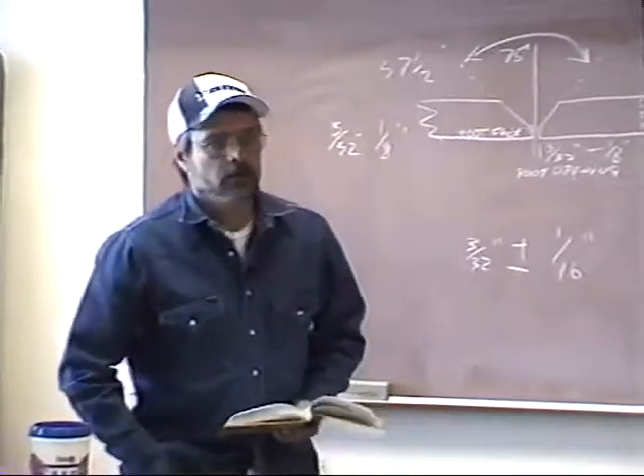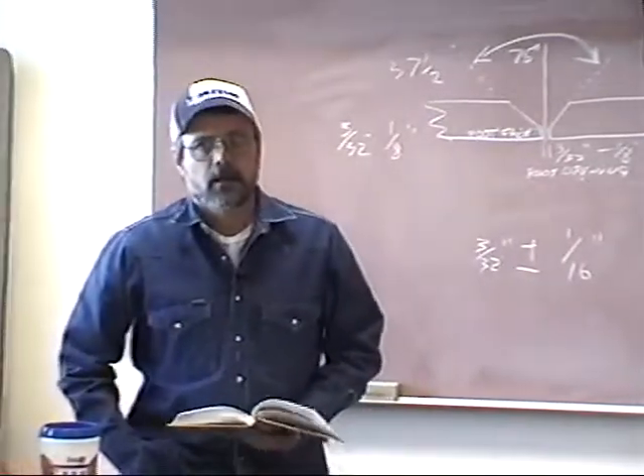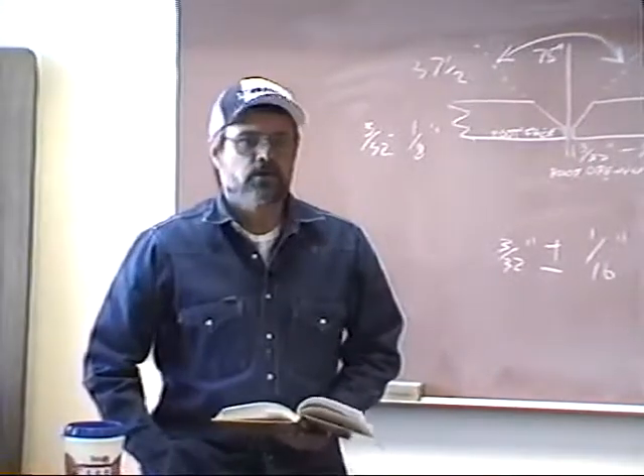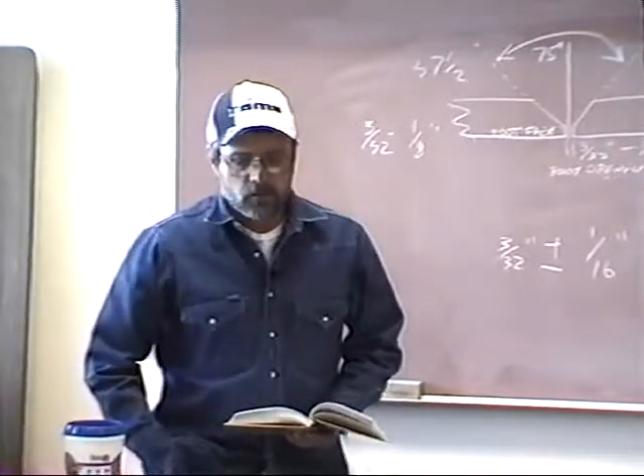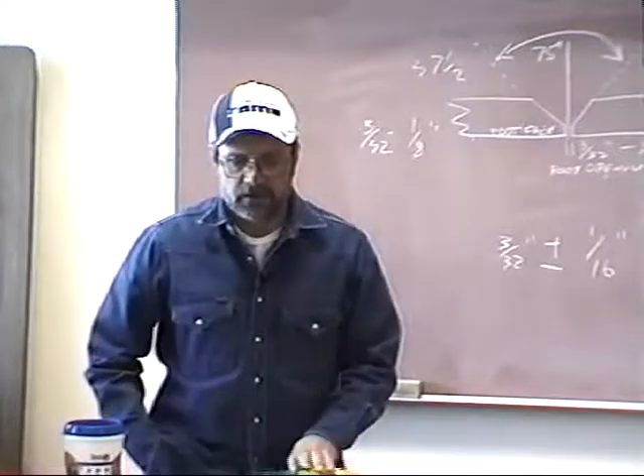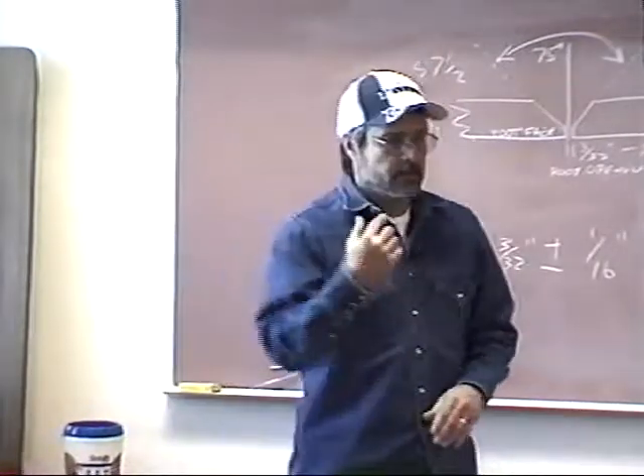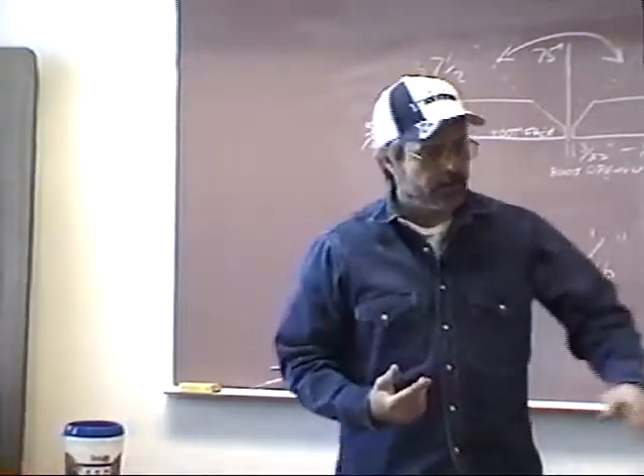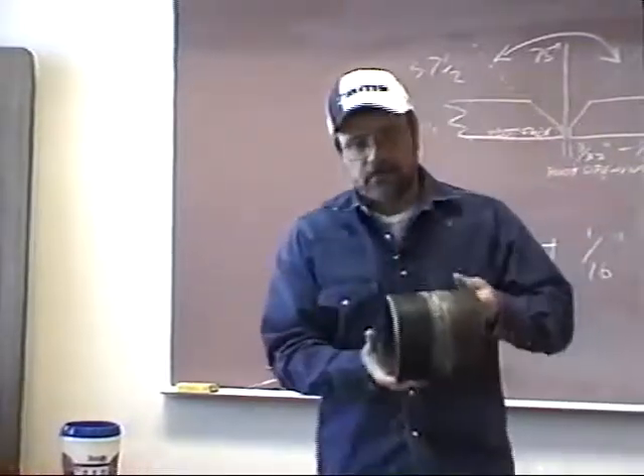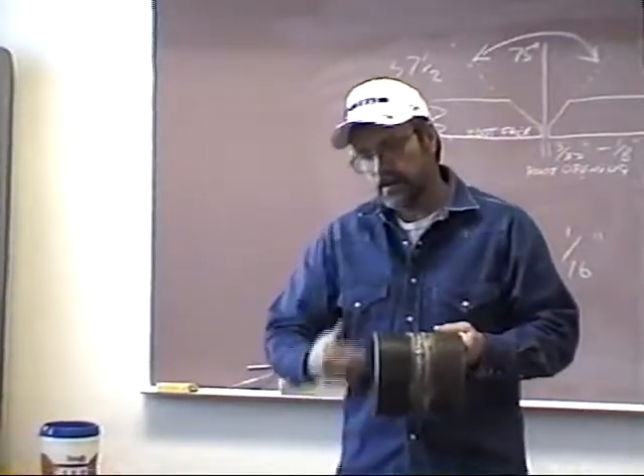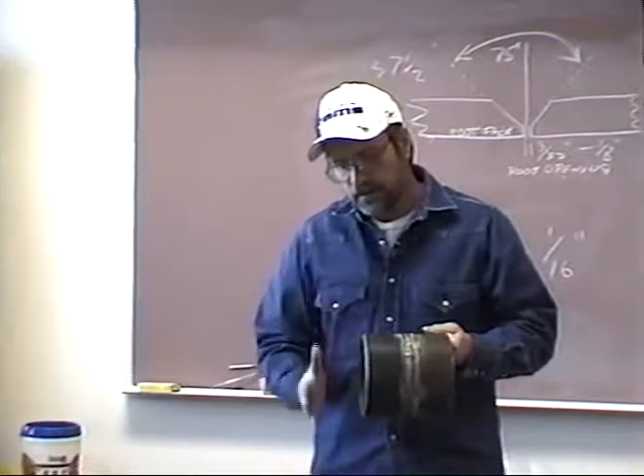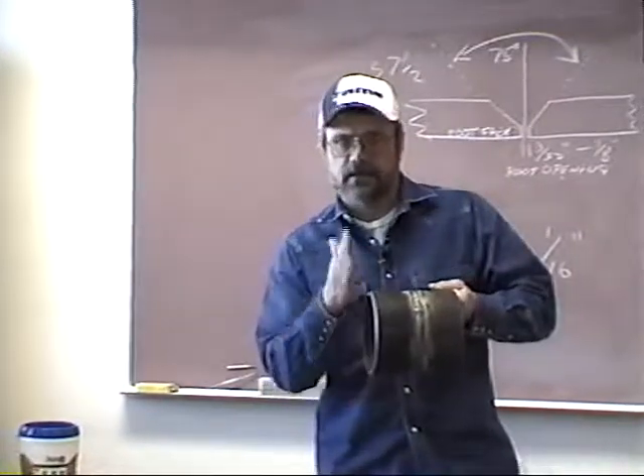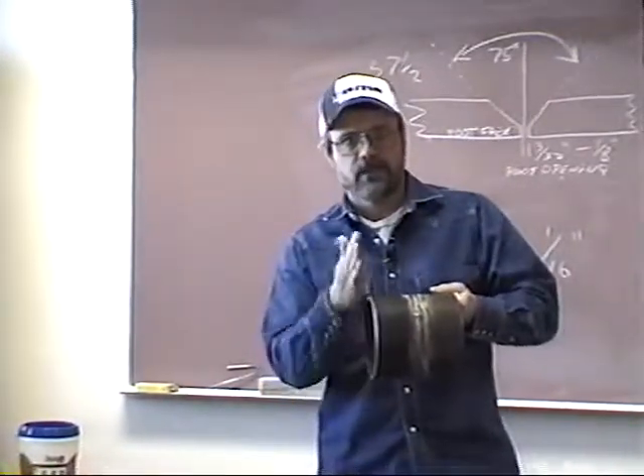But if you have to hand bevel a piece of pipe, unless you're really good with a torch, it is pretty tough. And the one thing about hand beveling a piece of pipe that you need to bear in mind is that the cut that you make on the top of that pipe, if you've got that pipe like here, and you've made this cut, the most important thing to consider is how square is that face? How square did you keep that face?